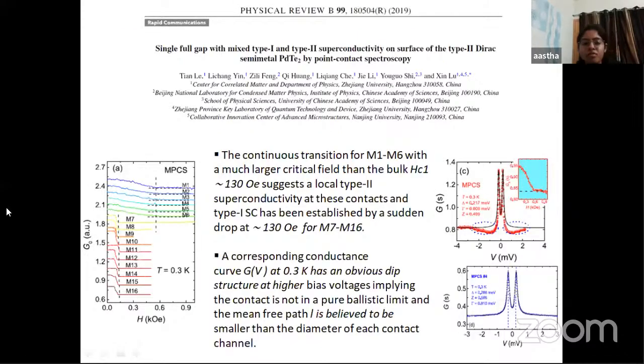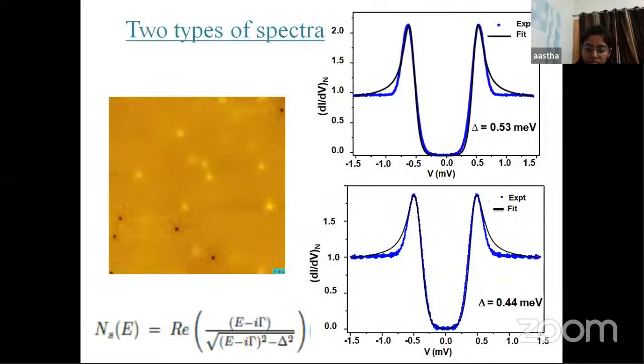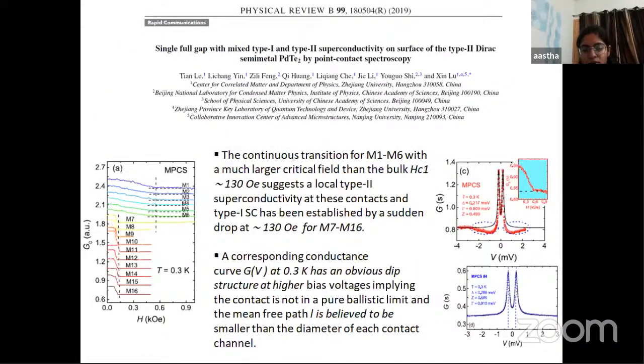Just after the publication of our paper on mixed type 1 and type 2 superconductivity on the surface, another Chinese group reproduced our results, and they also concluded that the inhomogeneity in the mean free path is responsible for the type 1 and type 2 regimes. So, as I have already told you, the inhomogeneity in the mean free path is responsible for the different critical fields observed on the surface of PdTe2.